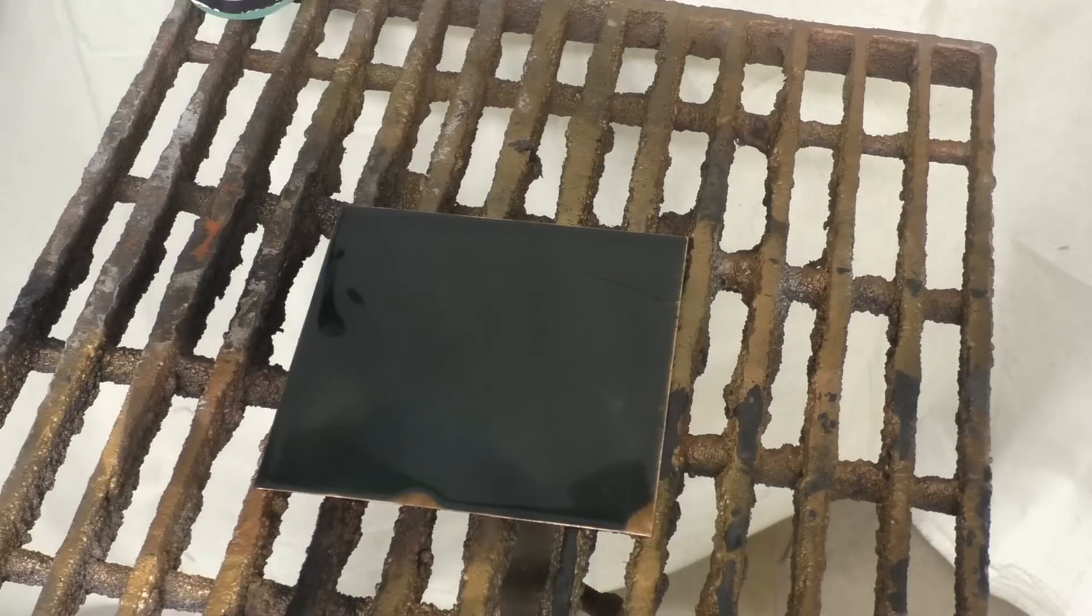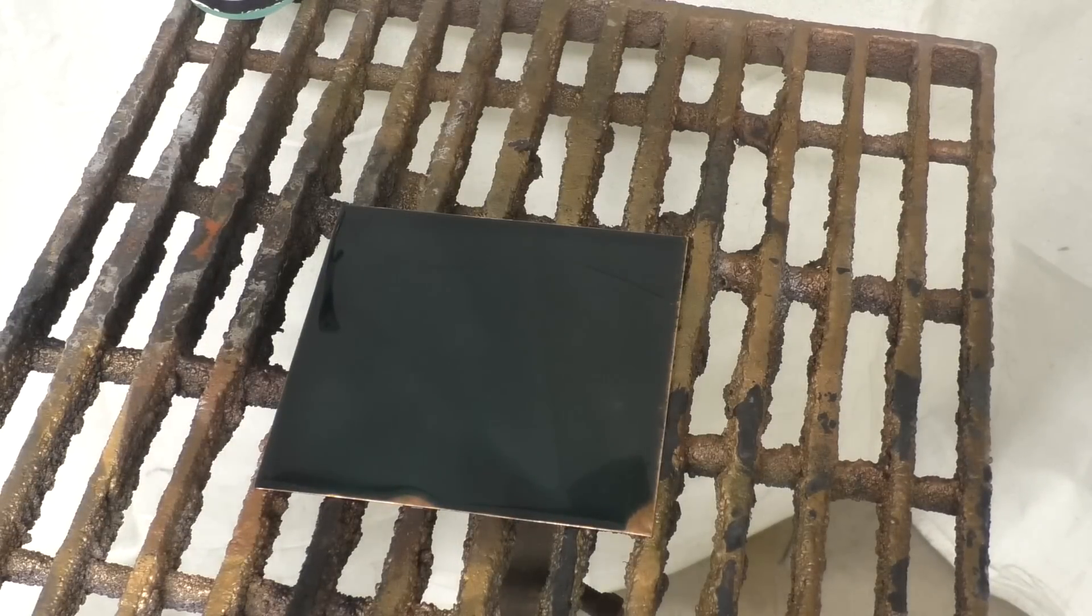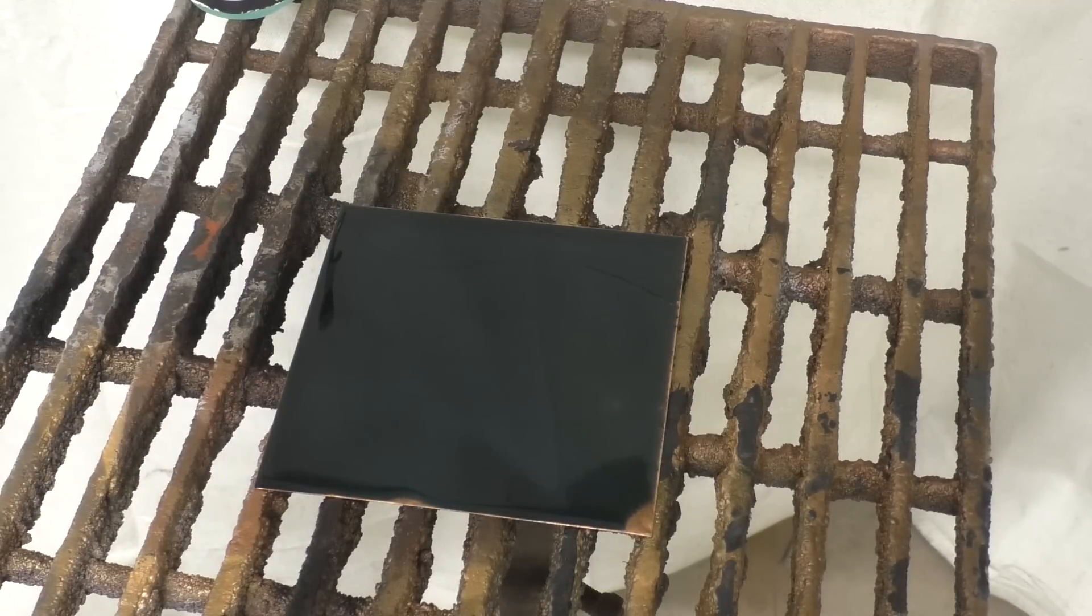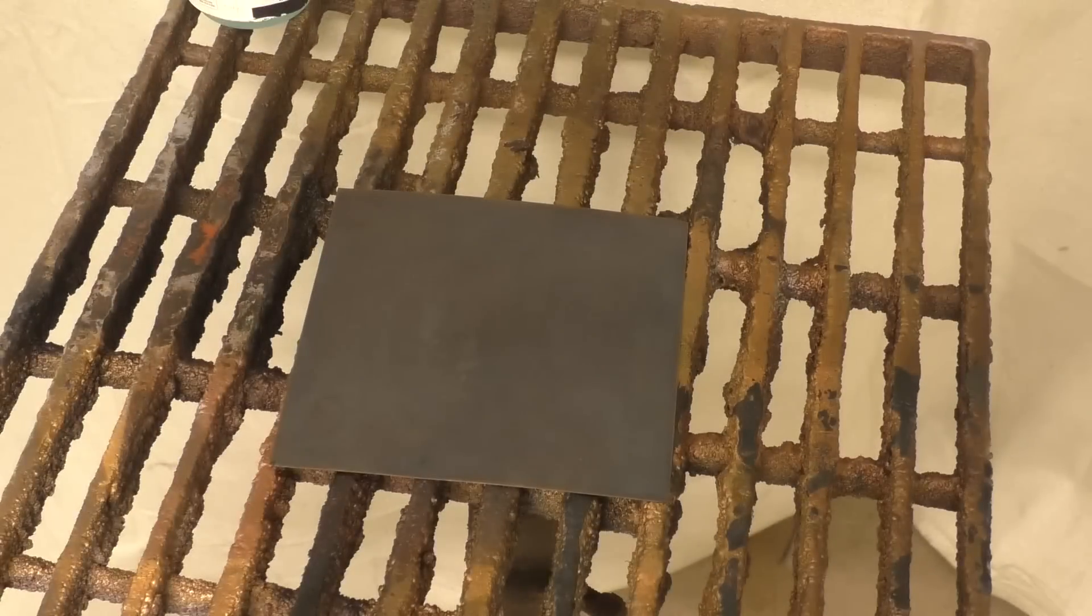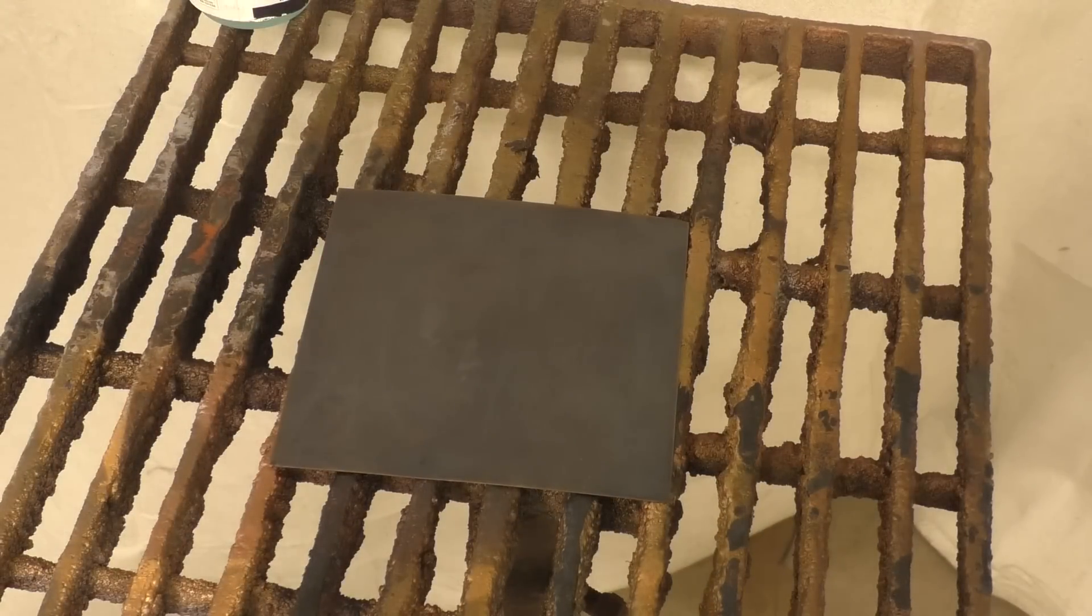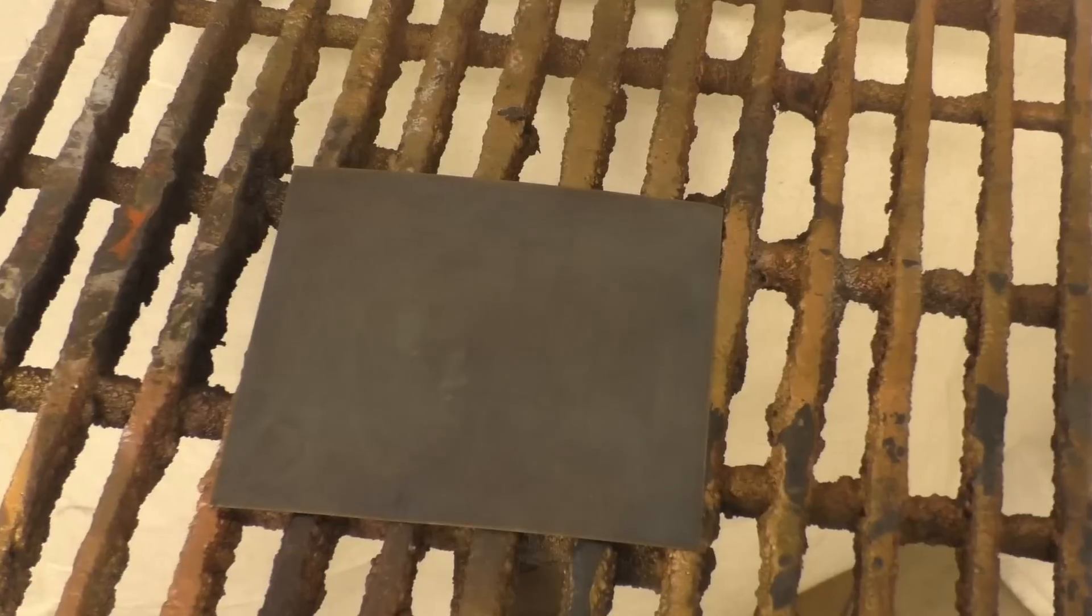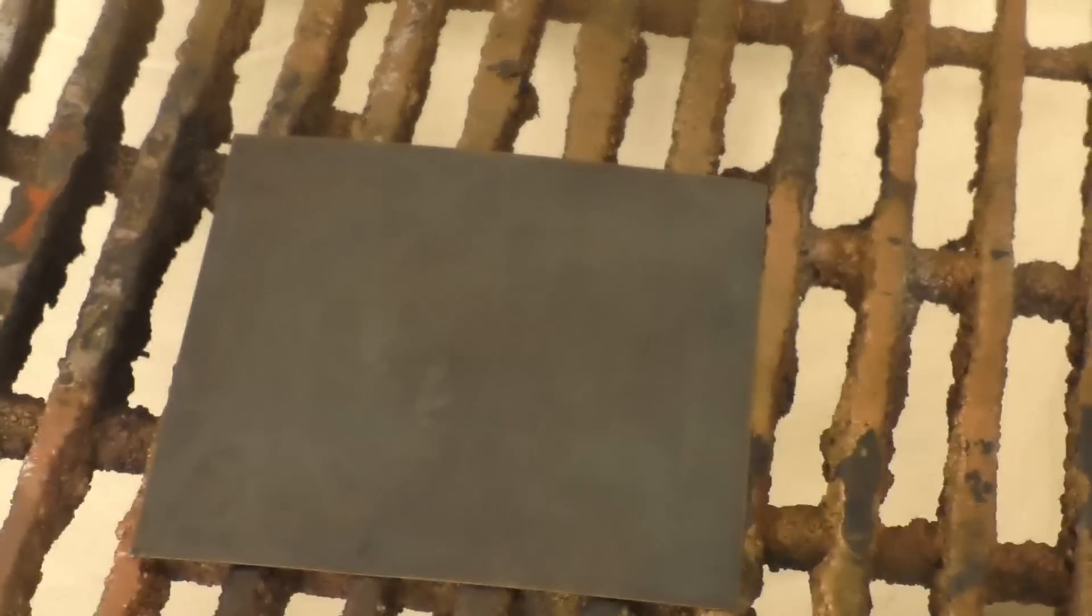All of these are the same concentration for the patina, so it kind of shows what it can do on one coat at two to one. A lot of times I'll do a three to one, but overall more coats, more concentration, the darker it is. Here we have our copper piece with M20 on it, came out a really nice kind of grayish brown blackish brown, just like the bronze and brass as we expected.